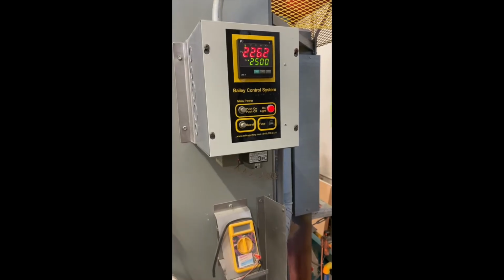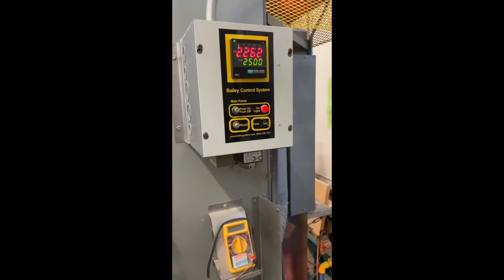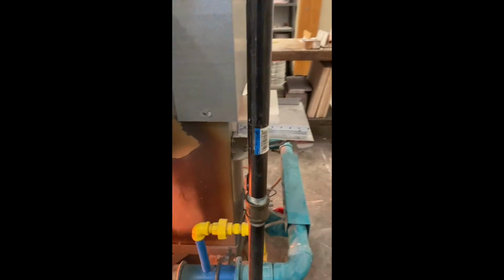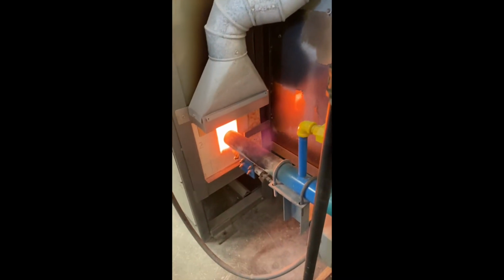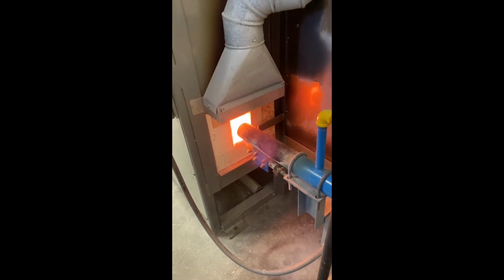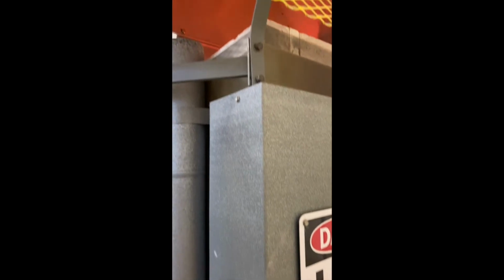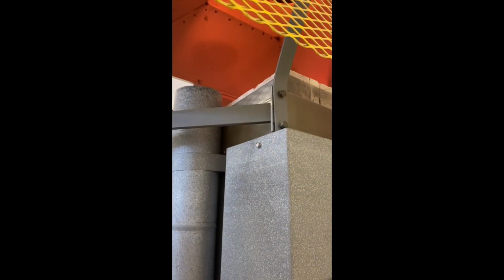Here we're nearing the end of the firing and we're at 2262. We're looking carefully at the last two cones, cone 9 and 10. You can see the heat is much higher now. We see the damper is still in for a slight reduction and the flame coming out of the chimney is visible.